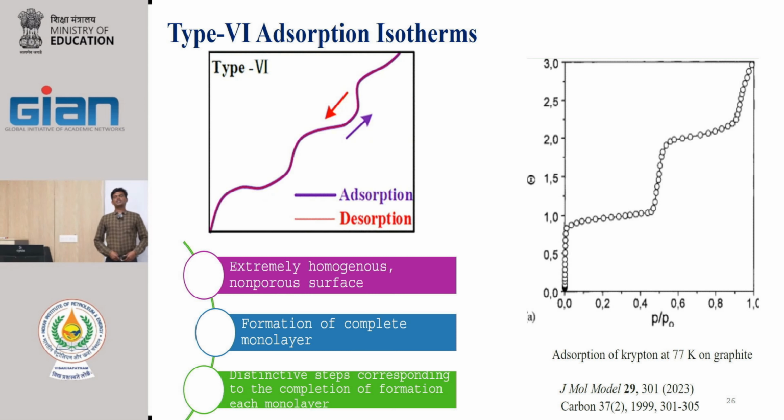Regarding metal organic frameworks, whenever we deal with gas molecules, it's still at the lab stage only. Whenever we do these things, adsorption and desorption follow the same pattern because most likely capillary condensation may not happen. However, it depends on the system. Whenever you try to separate CO2, methane, and so on, small gases, water vapor, using metal organic frameworks, adsorption and desorption follow the same pattern.